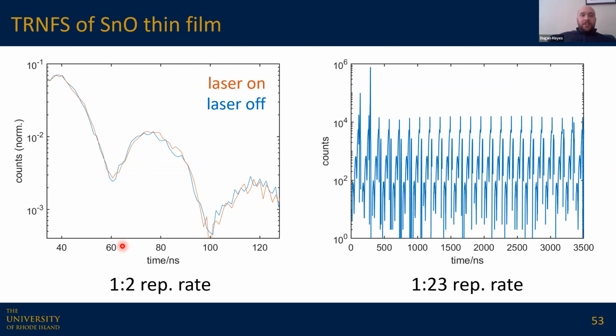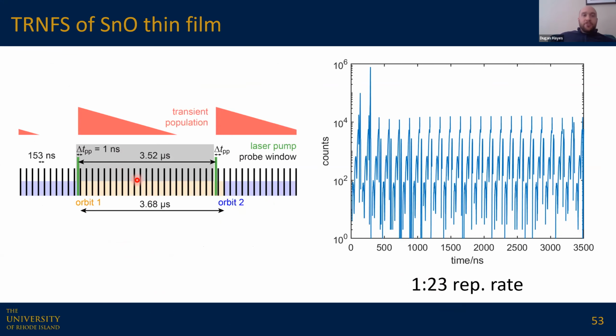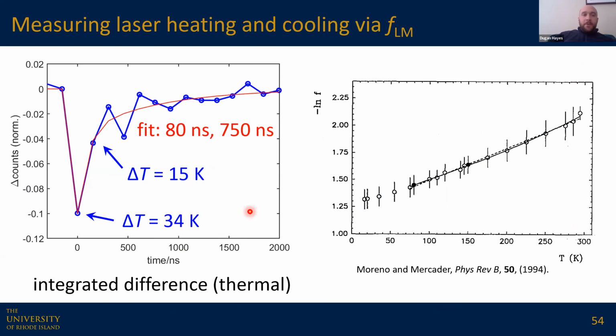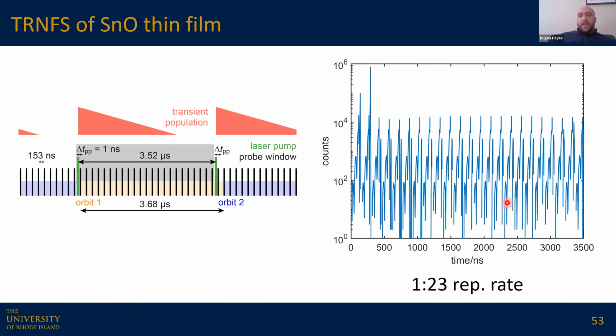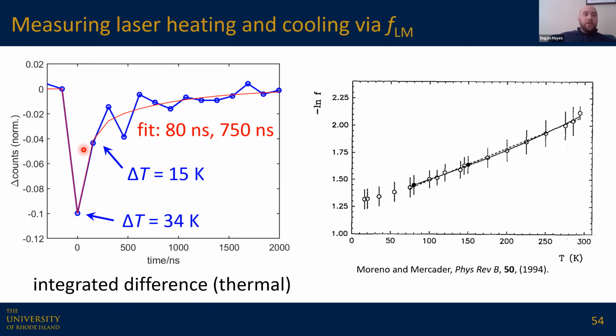And then importantly, we can change our laser excitation from half the repetition rate of the storage ring to 1/23 the repetition rate. We want to do this so that we average out any bunch-to-bunch differences between orbits by phase shifting as we go through every optical excitation. And so what we get here now is a drop. If we integrate the total counts that we have for each of those X-ray probe pulses, we can get a measure of the total nuclear absorption. And so this drop that we see with the laser corresponds to that laser-induced heating that's attenuating the overall spectrum.